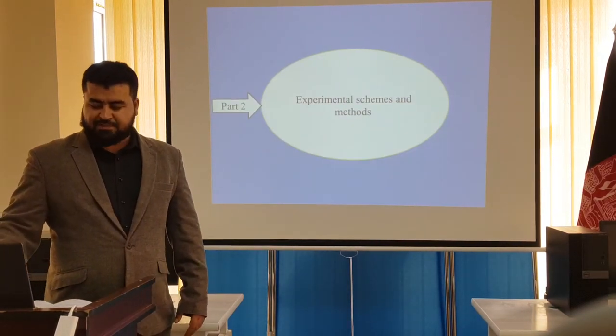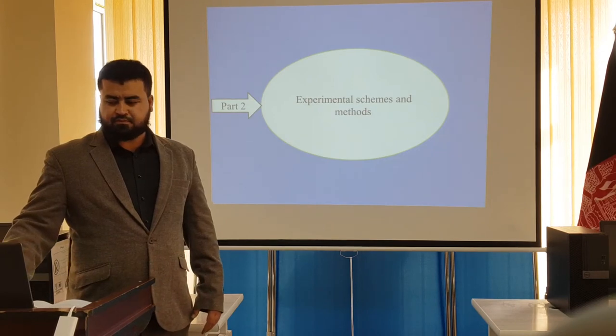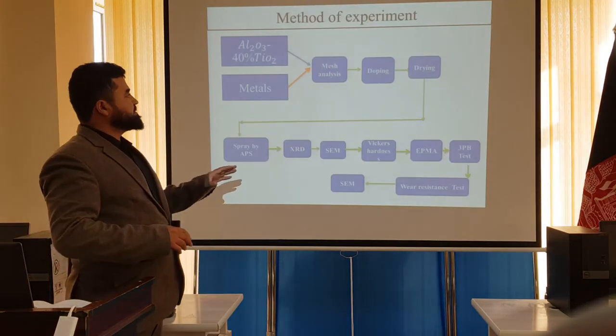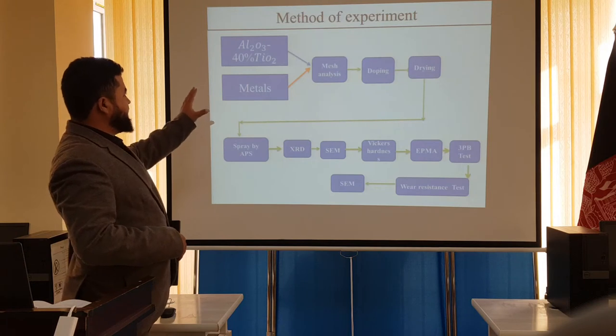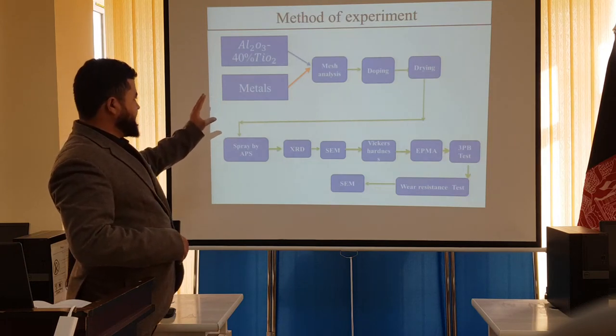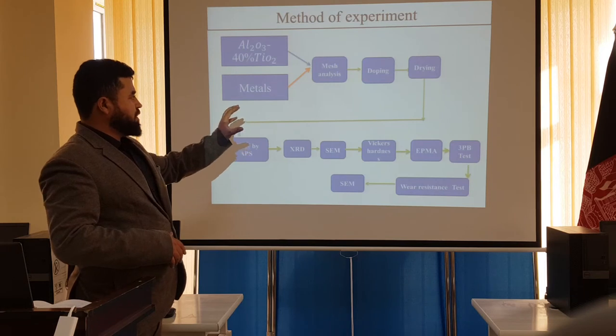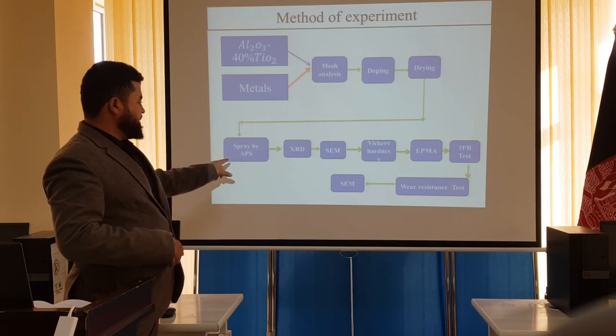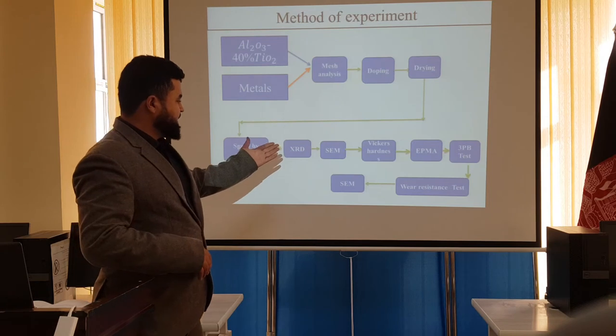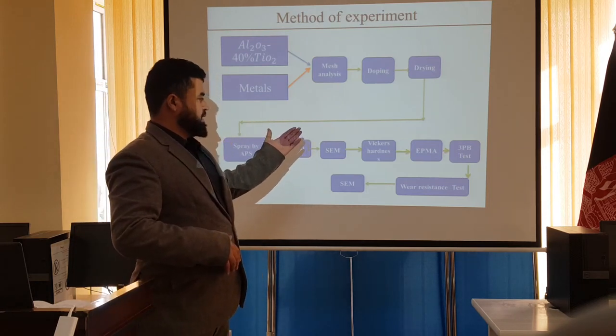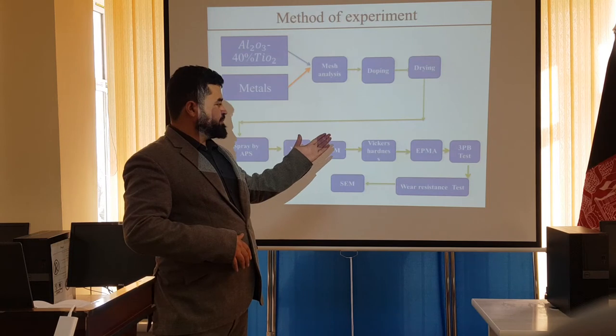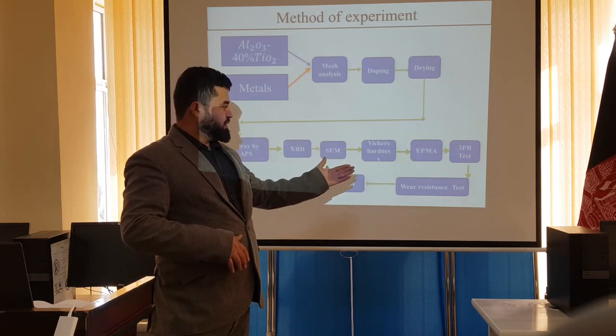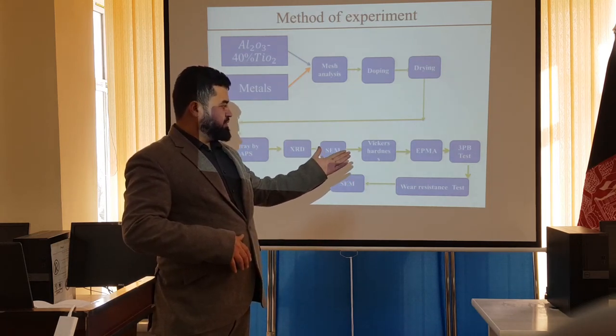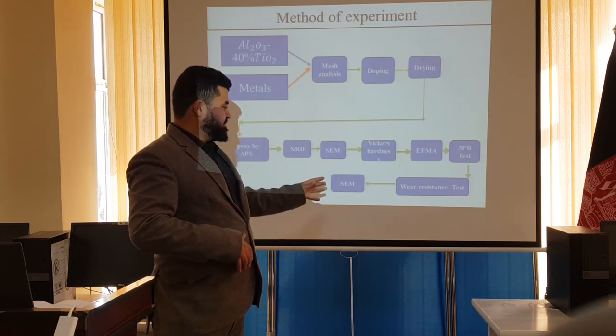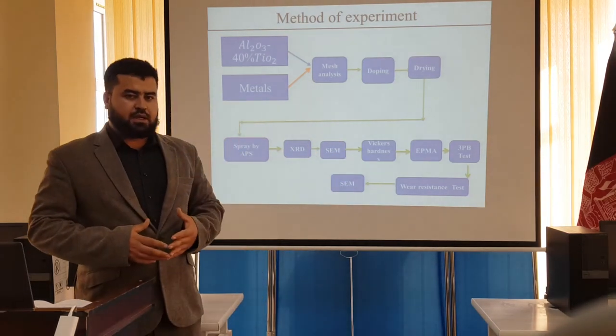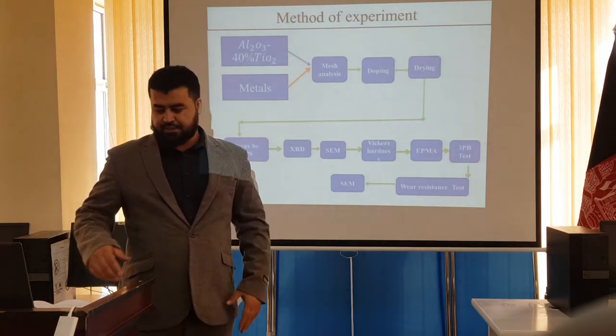Part 2. Experimental methods. In our experimental methods, we Al2O3-40%TiO2 metals after mesh analyzing, doping and drying, then sprayed by APS, then XRD, then taking pictures by SEM, then doing Vickers hardness, then taking images by EPMA, then doing the 3-point bending test, and finally we're doing the wear resistance test.